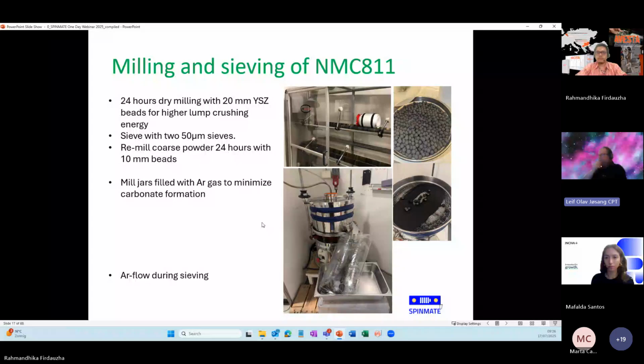So after calcination, we did dry milling. Most of you will probably have a smaller version of these mills in the lab. It's a simple roller mill. We used 20 millimeter yttria stabilized zirconia beads for the initial 24 hours. Then we separate this in a very coarse sieve and then move on to a stack of 50 micron sieves.